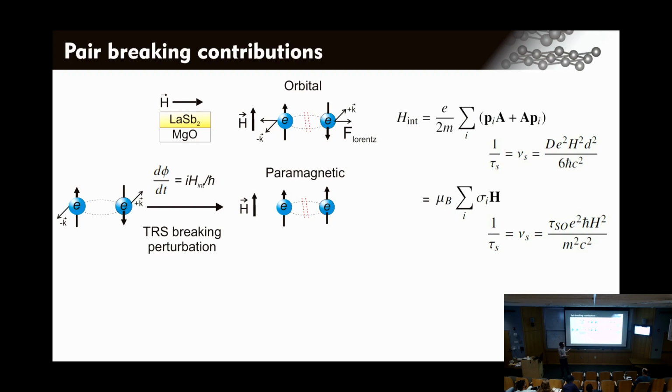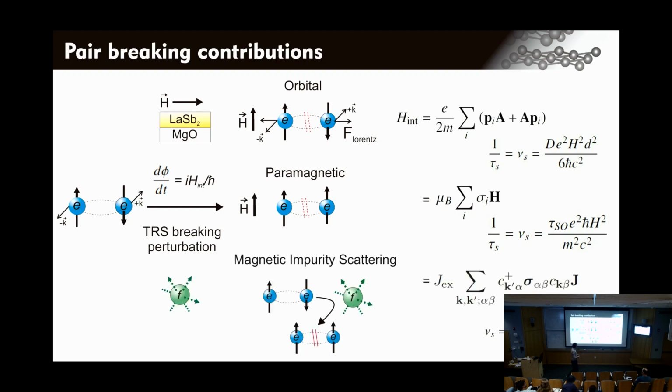So this is why I said before, it's not so surprising that we exceed the Pauli limit, because we have antimony and lanthanum. These are heavy elements, and spin-orbit coupling is going to be strong, which makes tau spin-orbit a very small number, which makes this effect small.